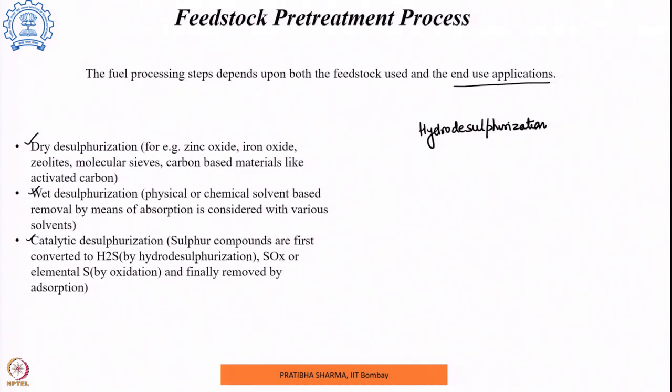First of all, the sulfur compounds are converted into H2S, and thereby it is finally removed by means of adsorption. So, herein hydro desulfurization is done such that all the sulfur containing compounds are converted into H2S. This is done at a temperature of 290 to 370 degree centigrade in the presence of cobalt molybdenum catalyst. So, this is a sulfur tolerant catalyst which is being used. Now, this H2S which is being formed here,